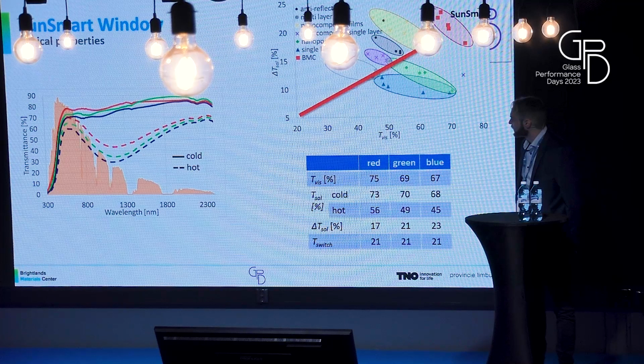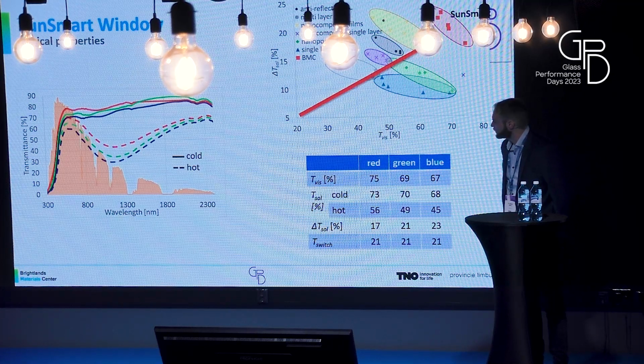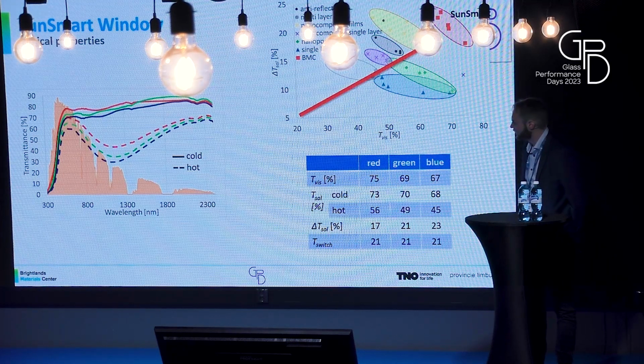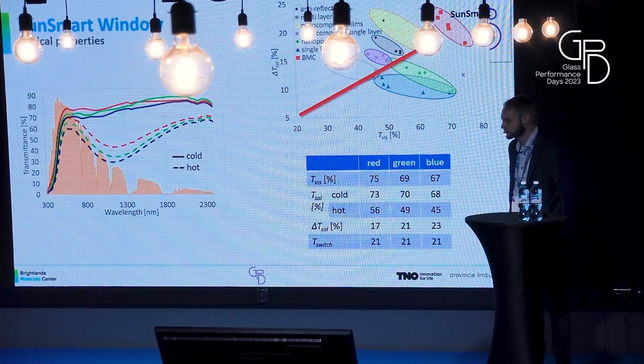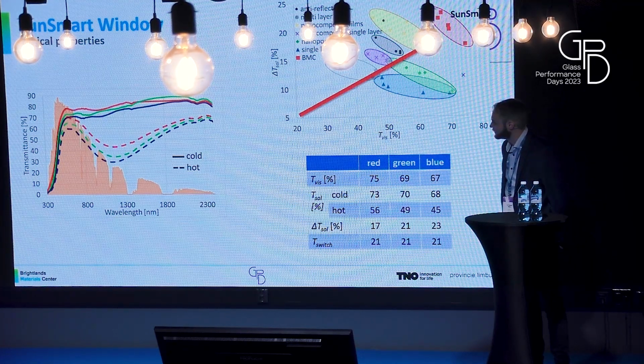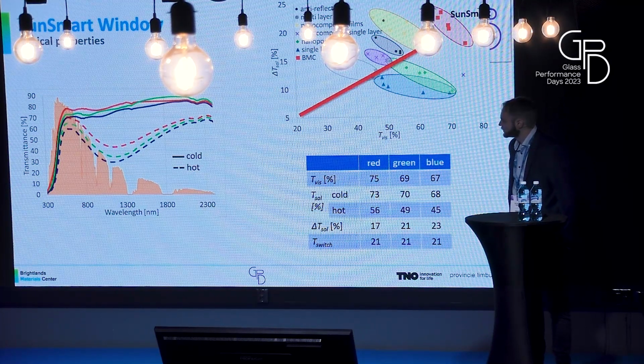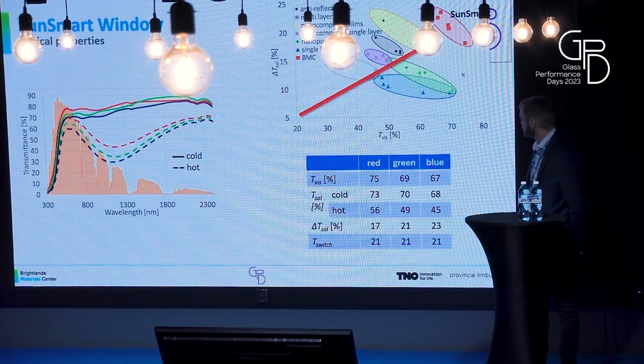so that you also have a proper modulation of your material. Here the most important part of the modulating area is in the region between 800 and 1400 nanometers, because that's where the major part of the infrared light is. So by optimizing that region, you can reach very high solar modulation properties.